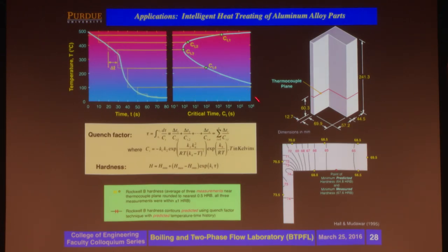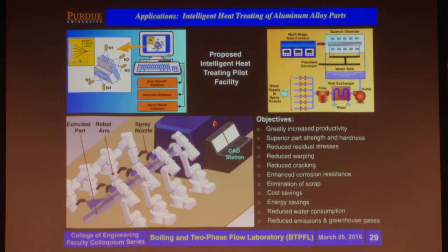So by this optimization process and changing spray boundary conditions all around the quenched part, we are able to do two things: achieve very high strength and very high hardness, and also achieve uniform properties without distortion. And you can do that by prediction. You don't have to run experiments by trial and error to achieve this result. Ideally, and that's something I've been trying to promote, and I'm talking to different people to do it, is to do all of this robotically by having robots lined up to quench the part from all directions based on predictions from a CAD system.